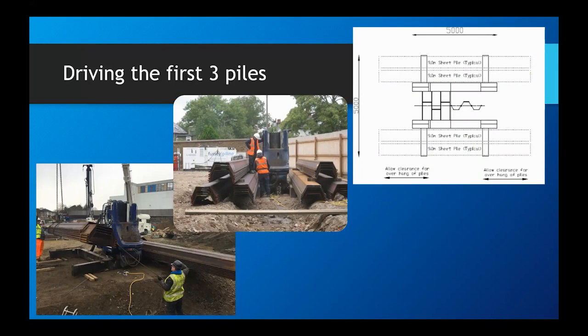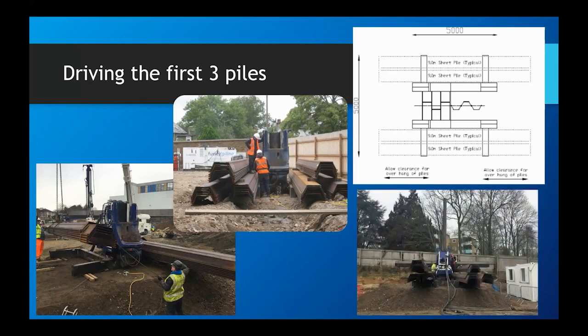We tend to put the sheet piles used for the project onto the reaction stand, which is about 50 or 60 tons of kentledge to react against. You use that reaction weight to pull against to install the first 3 piles, and that's a back view of it.